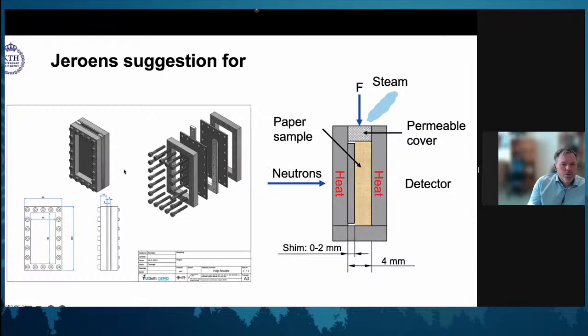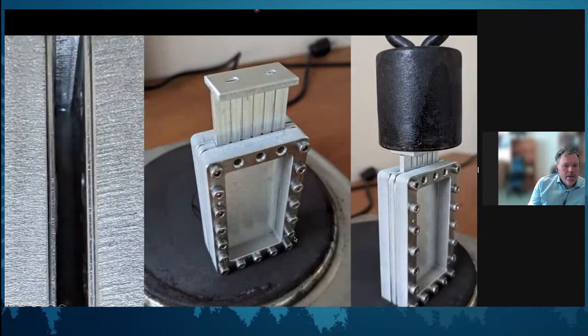We can send the neutrons into this and have the detector on the other side and image what happens to this when heating. So it was a very simple setup, and that turned out to be really good. Talk about heating. We didn't choose the most complicated heating mechanism. This is a heating plate. It's a stove that was put in a neutron beam. So you could actually lift it up to get in contact with this aluminum wafer system.